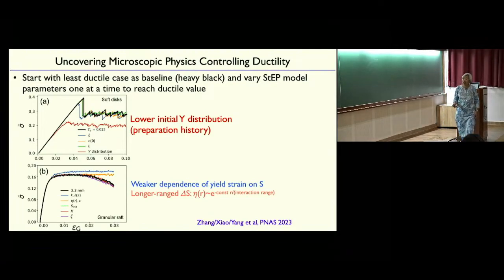Again, we changed them all one by one. And the thing that matters, I'm going to focus on this one, is that it depends on the range over which you affect the softness of spectators, the near field piece. The range of the near field piece turns out to be roughly the interaction range in particle diameters. And that's what changes the system from having more strain localization to less strain localization.